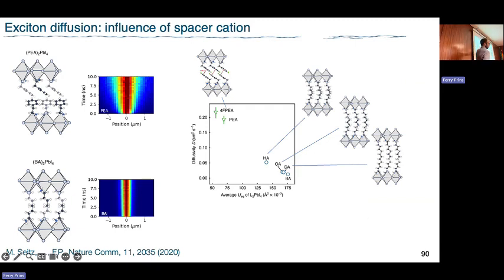So then we have the additional correction on it, which is the dielectric screening: depending on the dielectric constant of what surrounds your particle, you're going to get smaller shifts, but still shifts in the emission spectrum. You see clearly that the emission spectrum is slightly different from different organic cations.